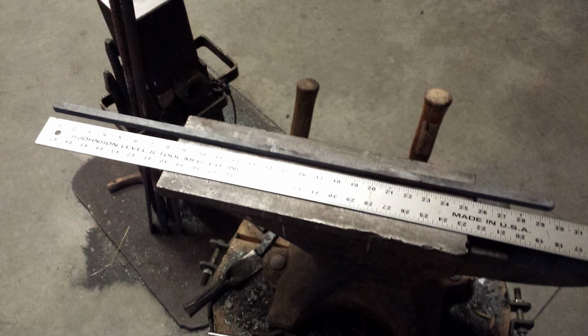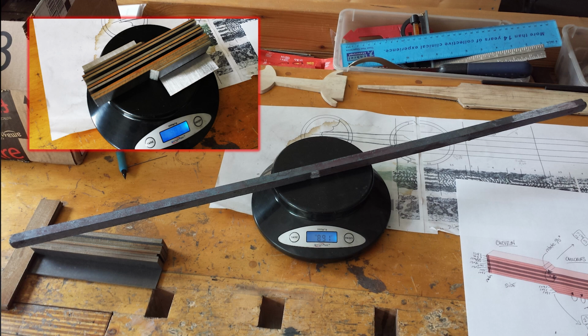Here's the billet warming up in the forge, all welded up and drawn out. Measures look about right. Remember that I had a lot of practice before to figure out what the lengths were that I needed, based on how much distortion occurs when twisting and drawing out. And the weight looks about right too. The billet was almost 1 kilogram, having lost about 100 grams during the forging process.